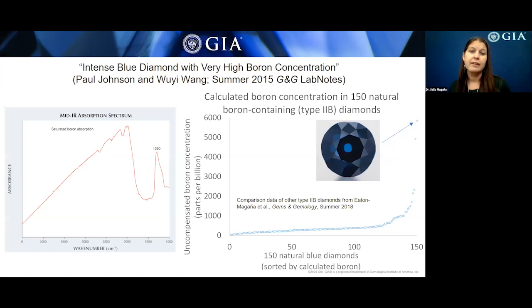On this slide, we're showing on the left the IR absorption spectrum for that type 2B diamond. Notice that there's so much boron in this diamond that the 2800 wave number peak is completely saturated, and they needed to use another boron related feature, the peak at 1290 wave numbers, to determine its boron concentration as 5,840 parts per billion. For comparison, the boron concentration in the IR absorption spectrum of the Hope diamond is 1,720 parts per billion.